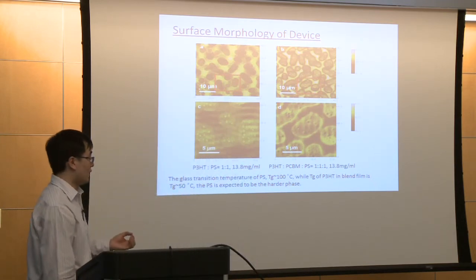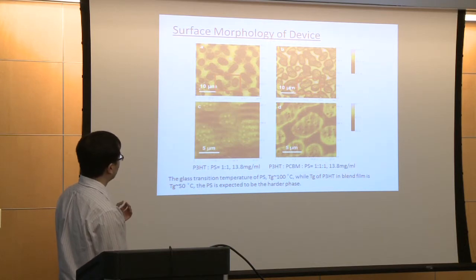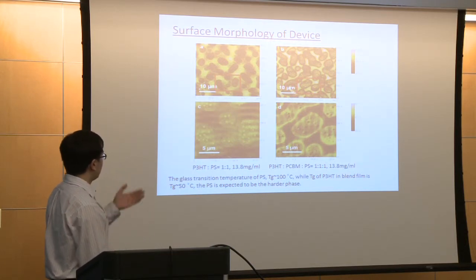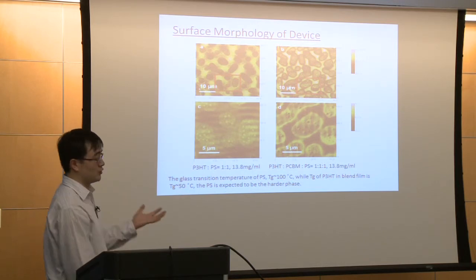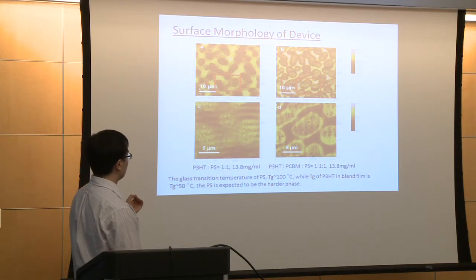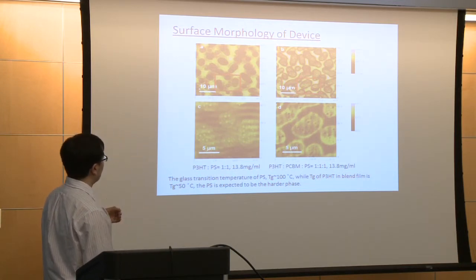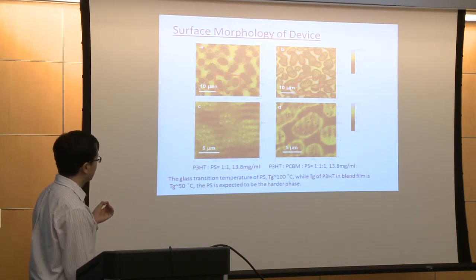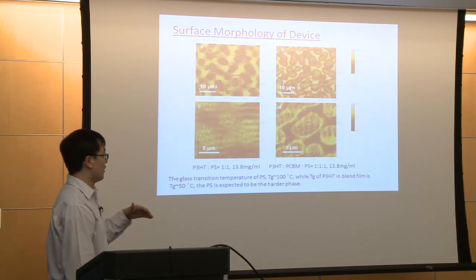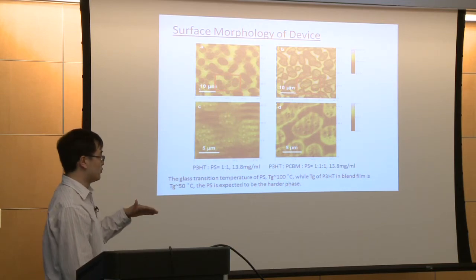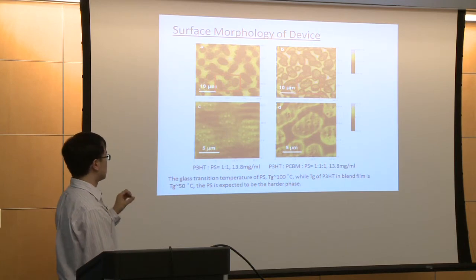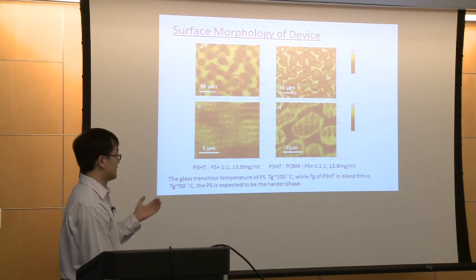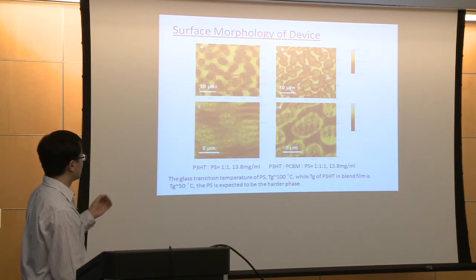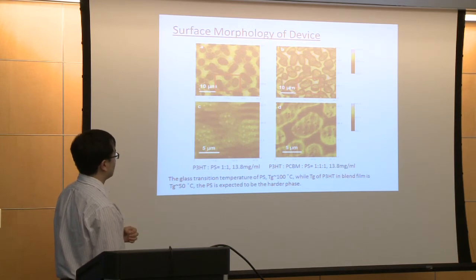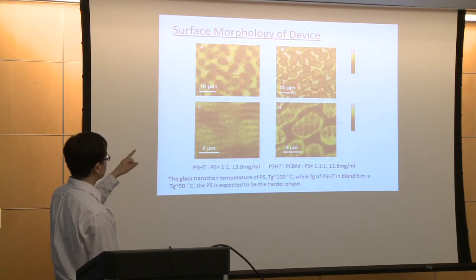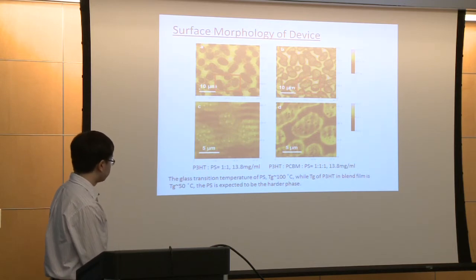Before we test our solar cell, we also take a look at the surface morphology by AFM. And we can see the surface morphology is almost the same as the film on the silicon wafer. Then we take a close look at some specific area, and we measure the lateral force of the area. Lateral force can reflect the hardness of the material. So the dark area means the harder material, and the light area means the softer material. Figures C and D are the lateral force images for the specific area within the red box.